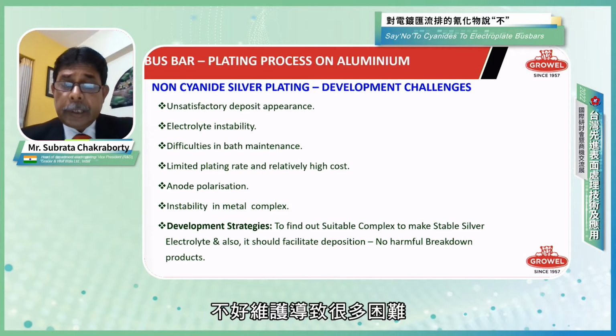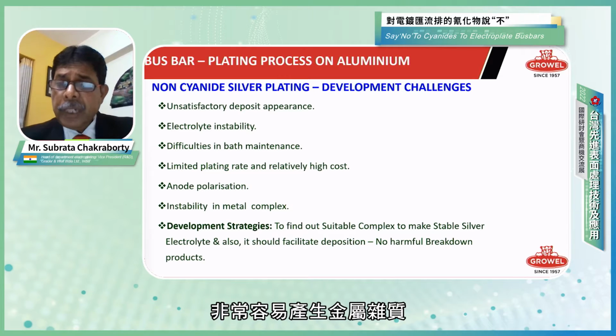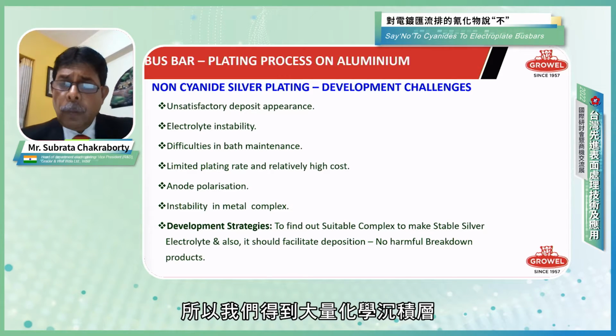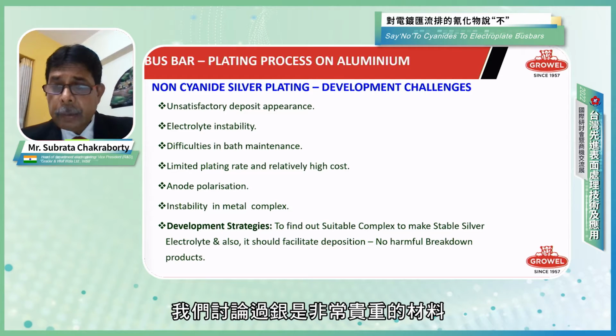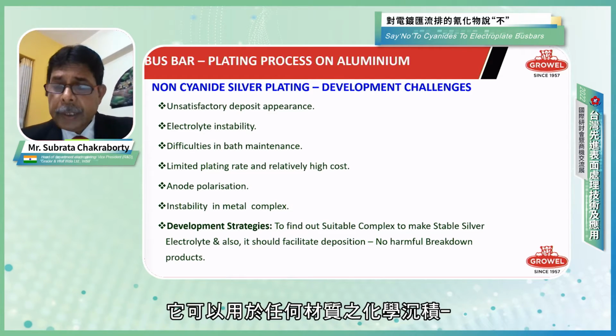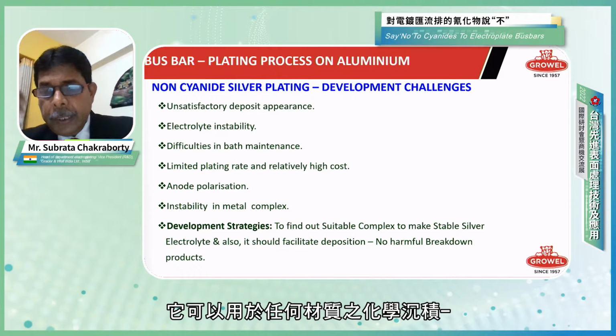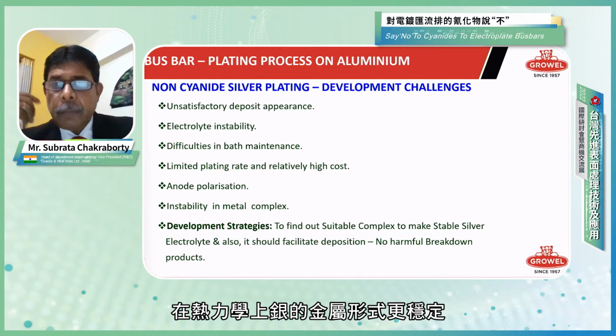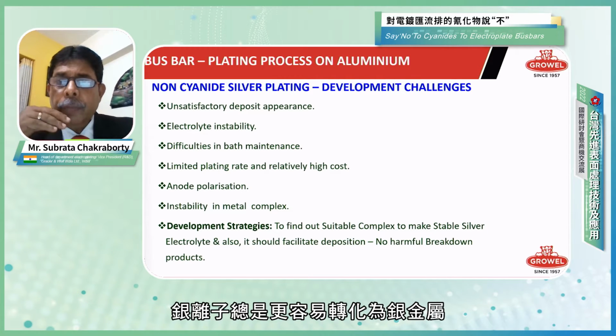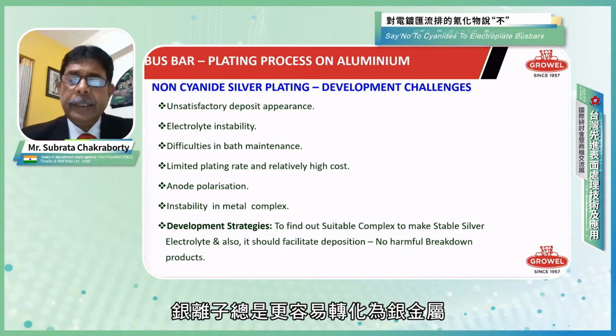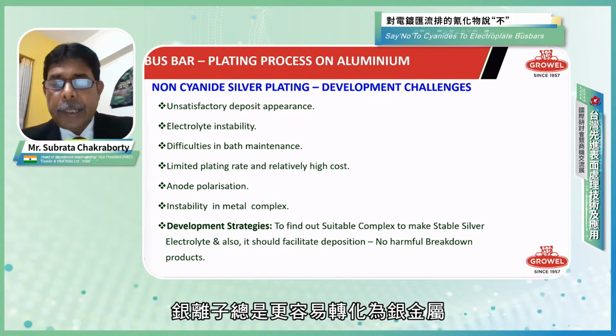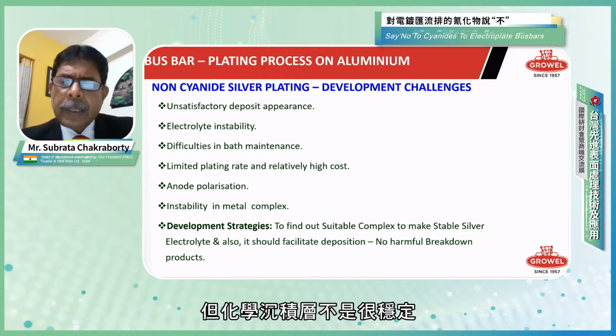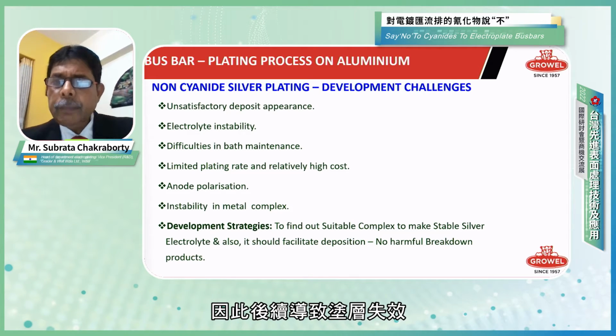A lot of difficulty with respect to bath maintenance, very much prone to metallic impurities. We were getting a lot of immersion deposit, because silver is very noble and can lead to immersion coating on any substrate, since thermodynamically silver is more stable in the metallic form. So from silver ion, there is always a tendency to get reduced to silver zero, silver metal itself. But these immersion coatings are not very stable, subsequently leading to coating failures.